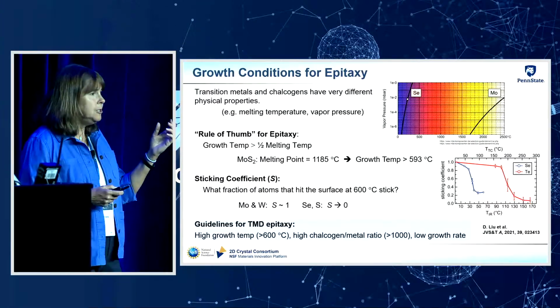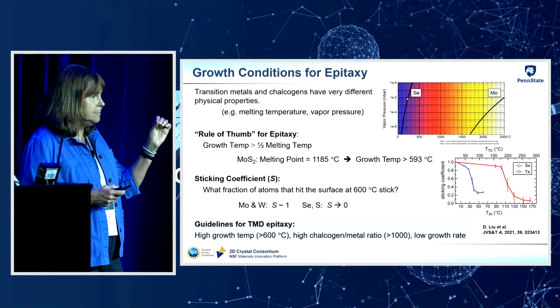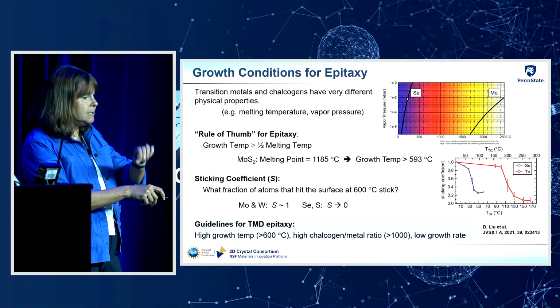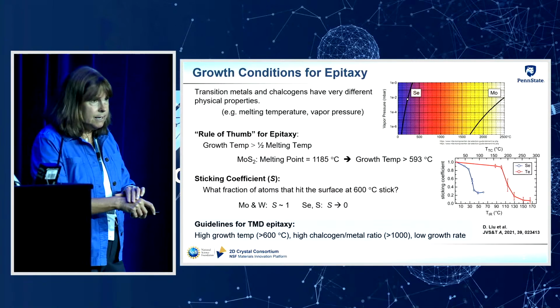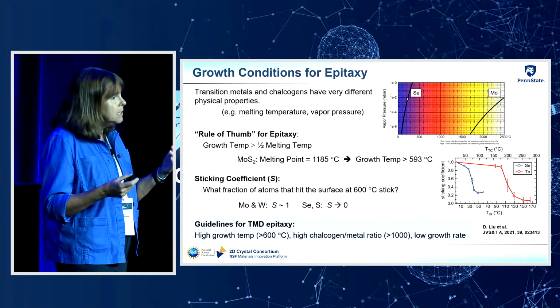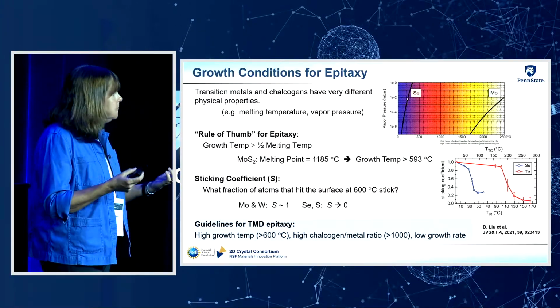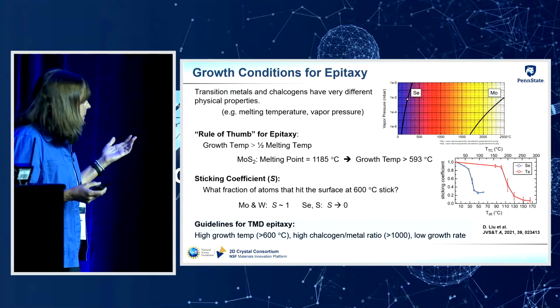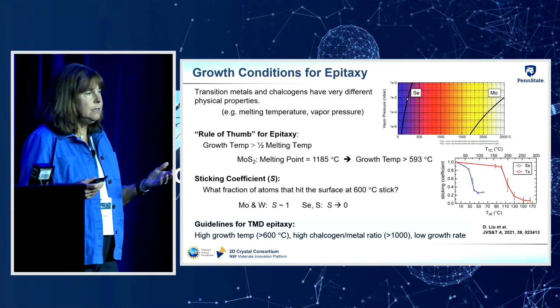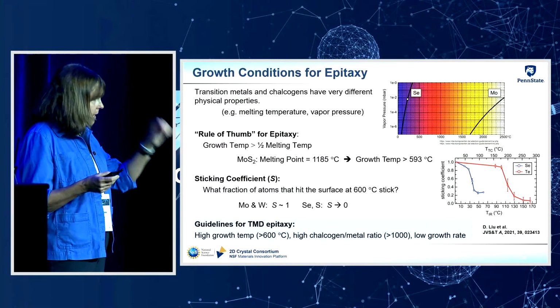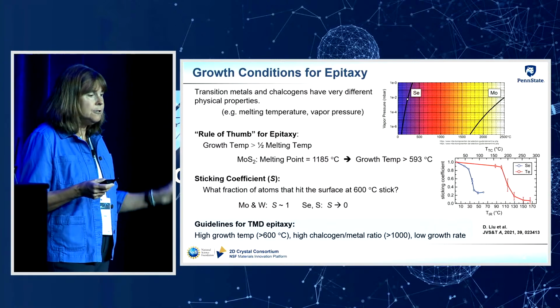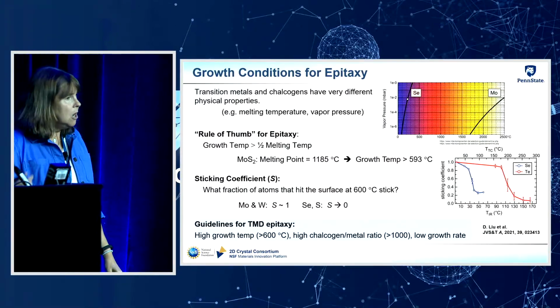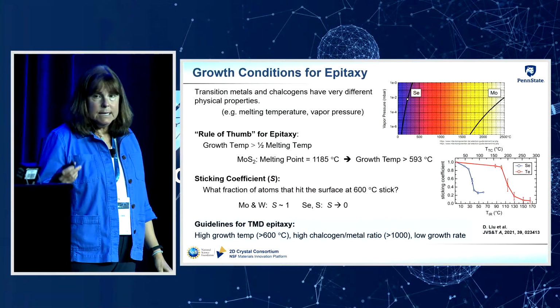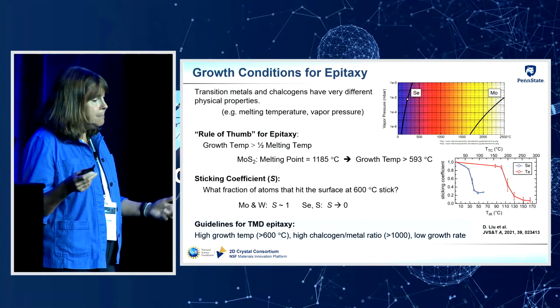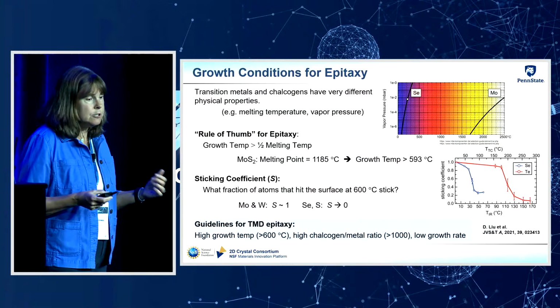So the sticking coefficient is basically the fraction of atoms that hit the substrate surface that are going to stick and be incorporated in the film. And that's related to the vapor pressure. So for elements like molybdenum and tungsten, the sticking coefficient is close to unity. Basically, every molybdenum atom that hits the surface is going to stick. In contrast, with selenium and sulfur that have high vapor pressures, their sticking coefficients are very small.